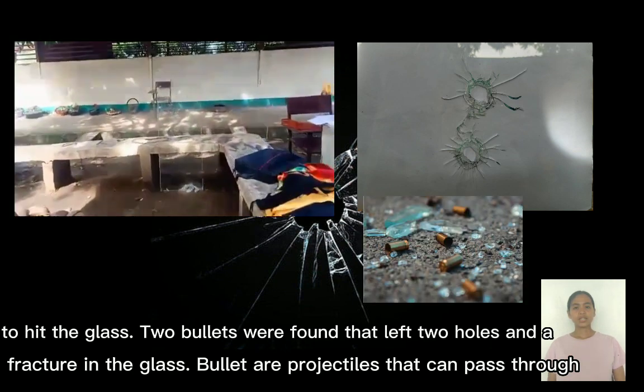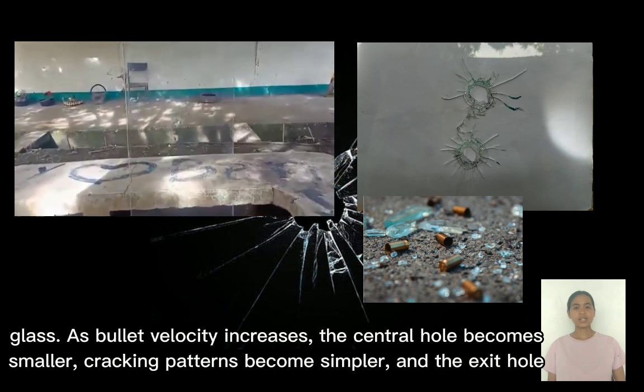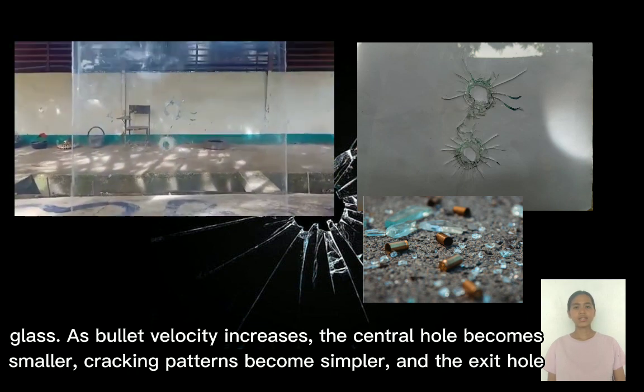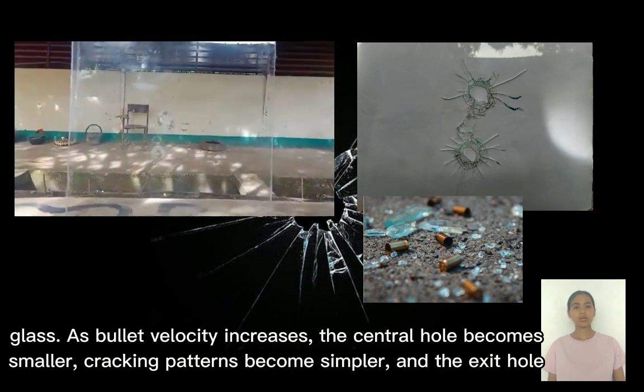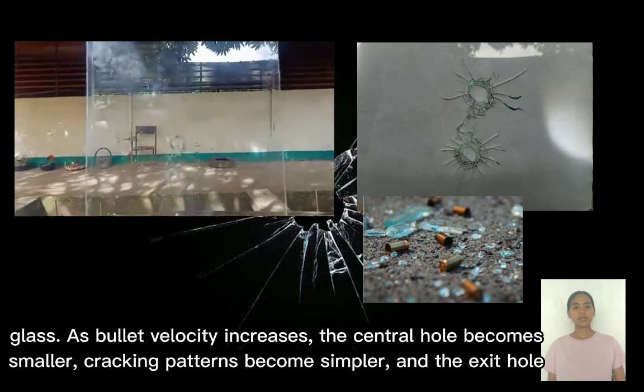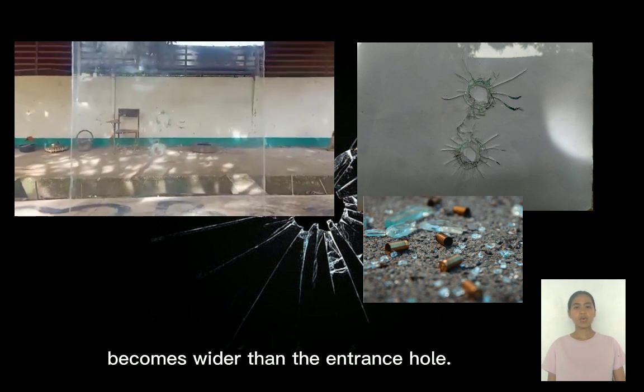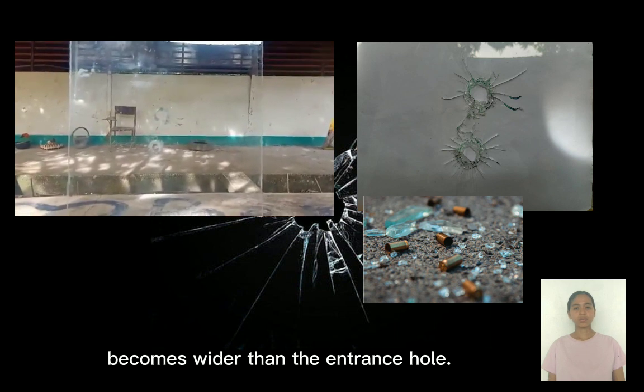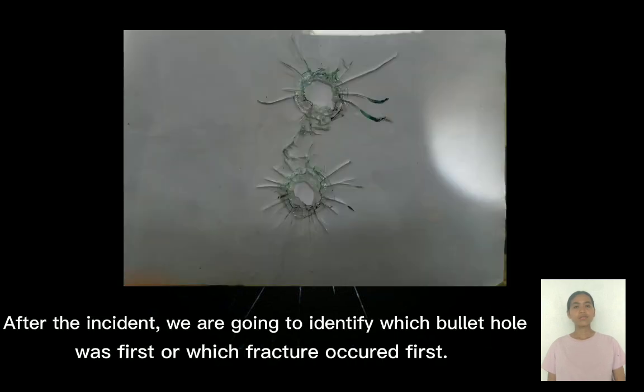Bullets are projectiles that can pass through glass. As bullet velocity increases, the hole becomes smaller, cracking patterns become simpler, and the exit holes become wider than the entrance hole. So after the incident, we are going to identify which bullet hole was first, or which fracture occurred first.